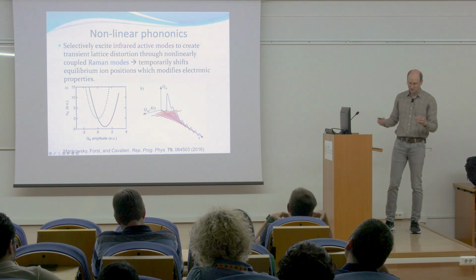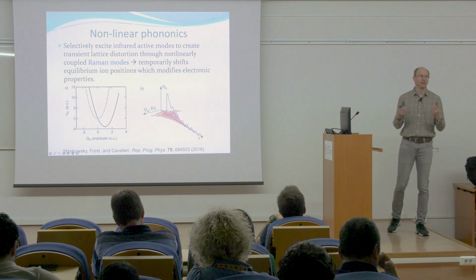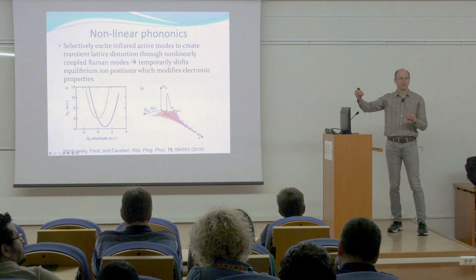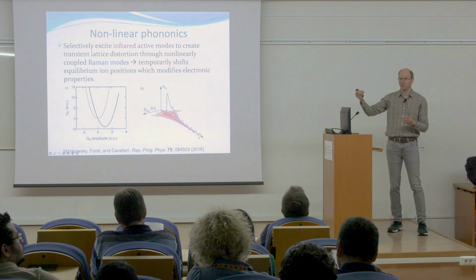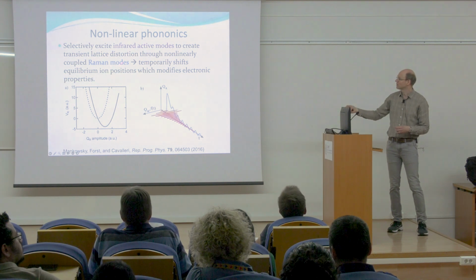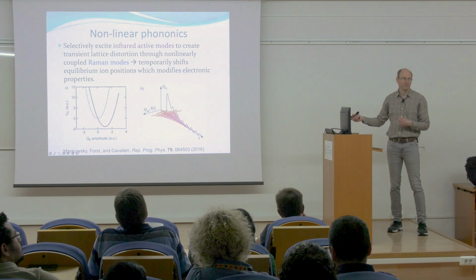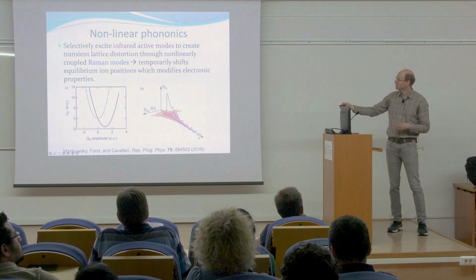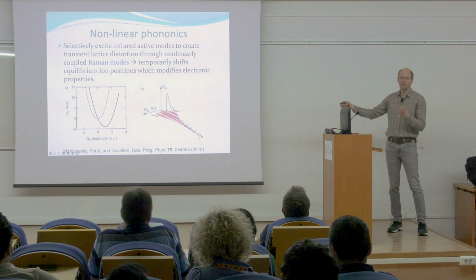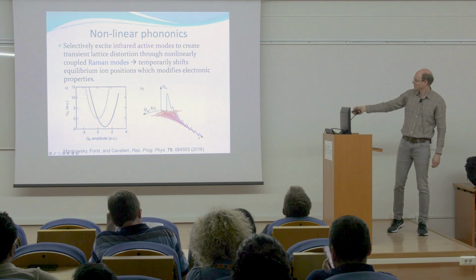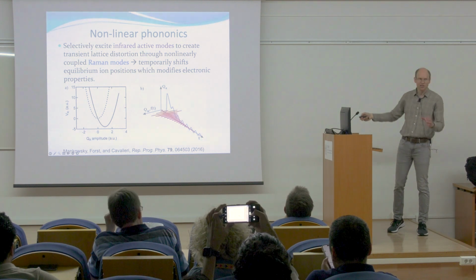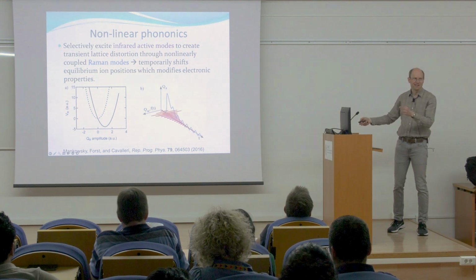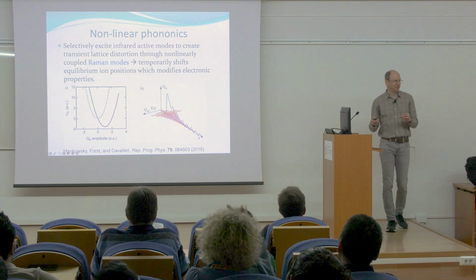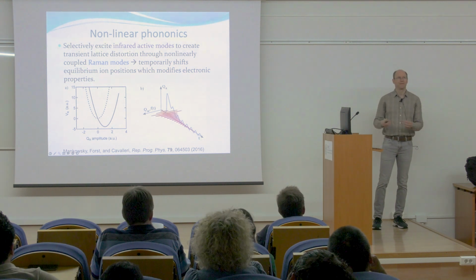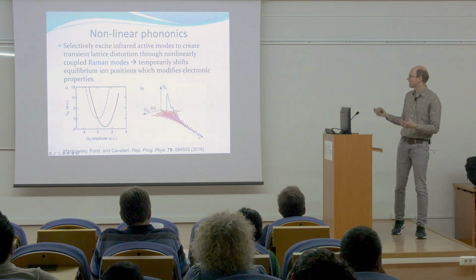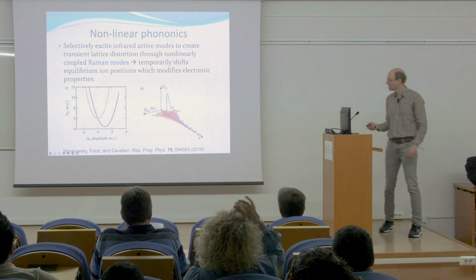So when you study phonons in a crystal, if the amplitude is low, then they basically follow a harmonic approximation, and you have a collection of harmonic oscillators. But if you create a large amplitude distortion, then you go beyond the harmonic regime. You have to include nonlinear terms. So you have nonlinear effects, and that turns out to couple the infrared and Raman modes to one another. And so you can therefore excite the Raman modes through this nonlinear coupling to the modes that you directly excite with the light, the IR active modes. And those Raman modes, when they're excited in this way, turn out to have a shift in the equilibrium position about which they oscillate. So there is a transient change in the symmetry of the crystal in this technique. So if you change the symmetry of the crystal, then you can change the sort of electronic properties of that crystal, which depend on the symmetries of the nuclei. So that's the basic idea.